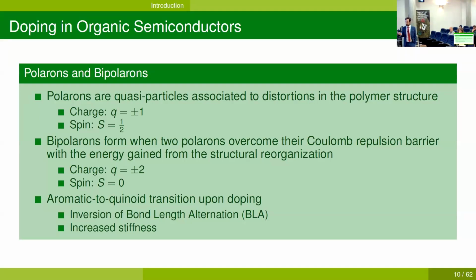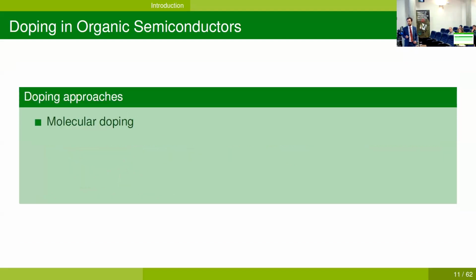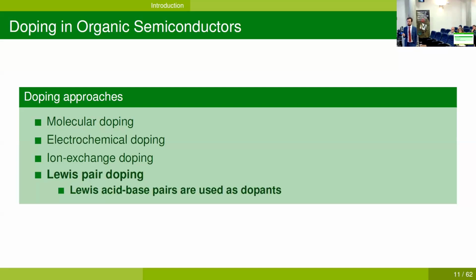So organic semiconductors undergo an aromatic to quinoid transition upon doping, which means that an inversion of the bond length alternation occurs, which means single bonds become double and vice versa. And they also experience increased stiffness or rigidity in the polymer chain. There are several doping approaches, such as molecular doping, electrochemical doping, ion exchange doping, but we won't get into much detail with this. What we will get into detail with is Lewis pair doping later.